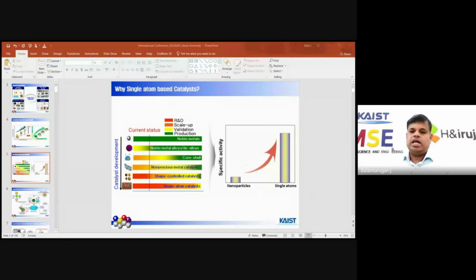When compared to nanoparticles, the single atom gives a higher specific activity, because of the more active sites compared to nanoparticles. In nanoparticles only the outside surface area is active towards the electrochemical performance; the inside core material does not get involved in the electrochemical reactions. Therefore the mass activity is very low compared to the outside surface area. With single atoms, each single atom is involved in electrochemical energy storage and conversion applications.